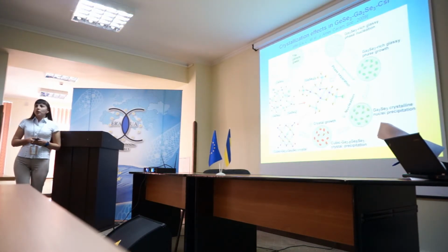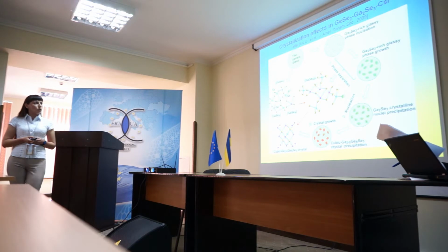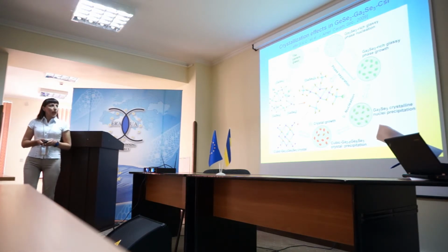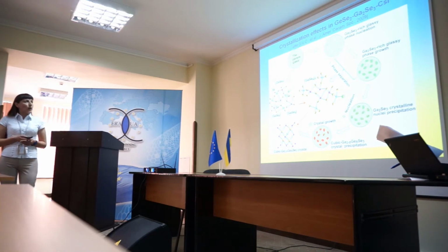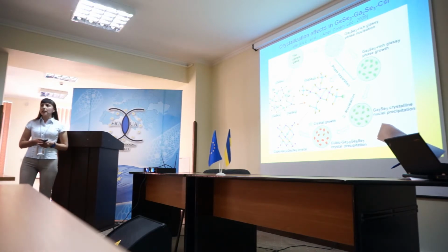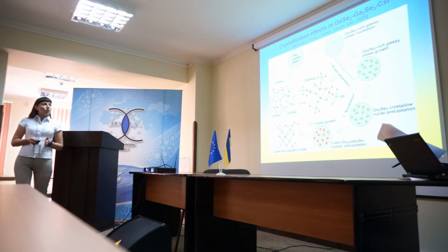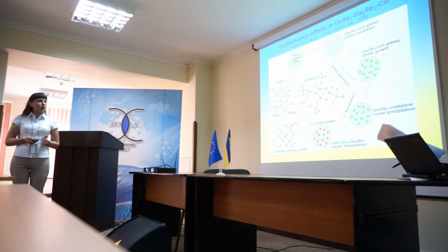In addition to the evolution of free volume, we have evolution in the formation of nanocrystals. Like in previous work, in our work we have nucleation in the initial stage of annealing, from 10 hours to 25 hours. In the next step we have formation of nanocrystals of 3 phases.